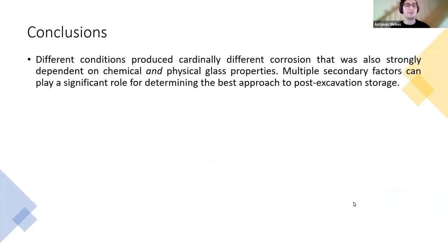So in conclusion, let's just say some partial conclusions for now. I'll start from a quite banal and necessary point that although there are general trends, it can be seen that the processes of glass corrosion are highly individualized. The object's appearance upon excavation and further reactions to the environment is strongly dependent on even small variations in chemical composition, history of exposure, size, physical defects, and so on. So it's very important to use as much information about the objects as possible.